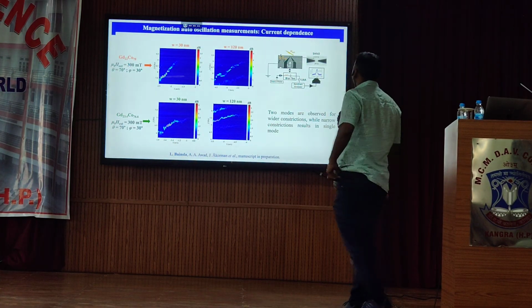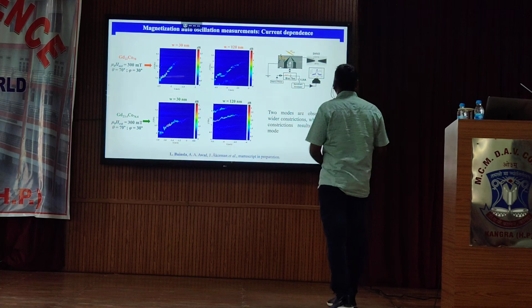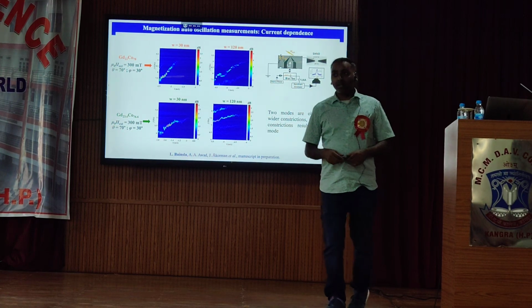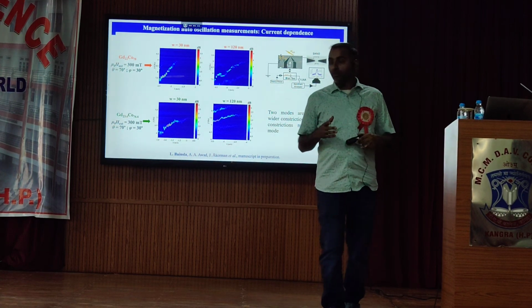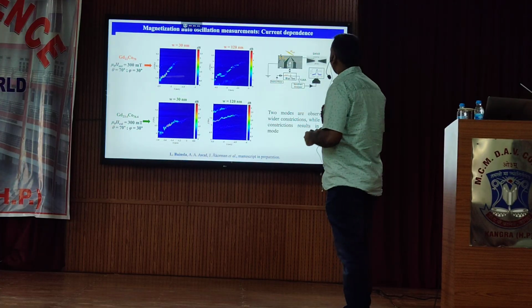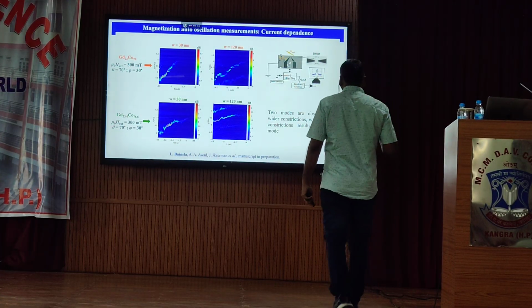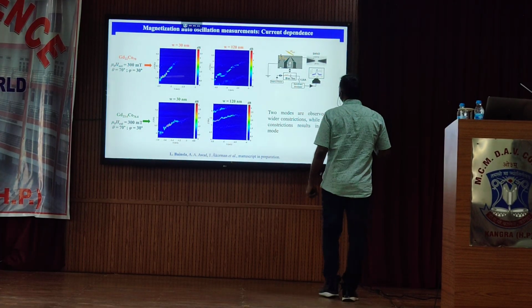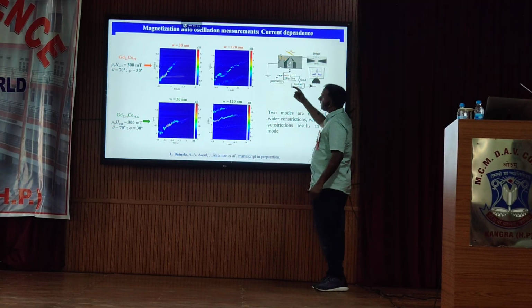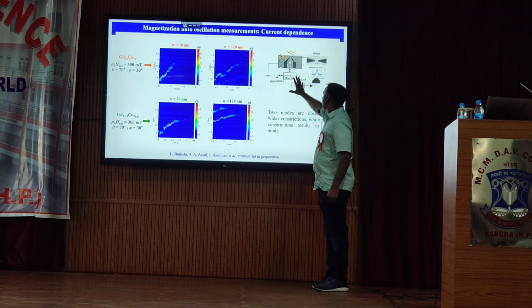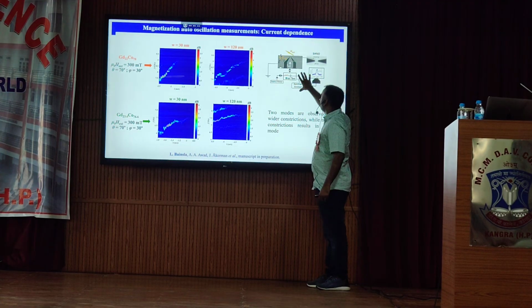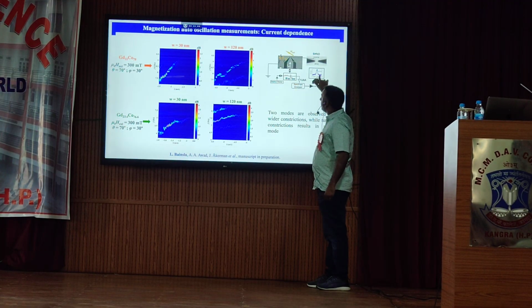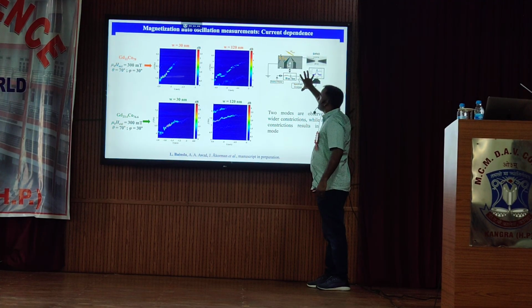Then we fabricate spin Hall nano-oscillators and measure those devices again using the same setup, for which I previously explained the optical measurement, but this time we did the electrical characterization. So this time we have not used any laser. We use the electrical characterization setup where we have a spectrum analyzer that can analyze the signal in the frequency range of 2 to 44 GHz. I will not go into the details of the analysis.